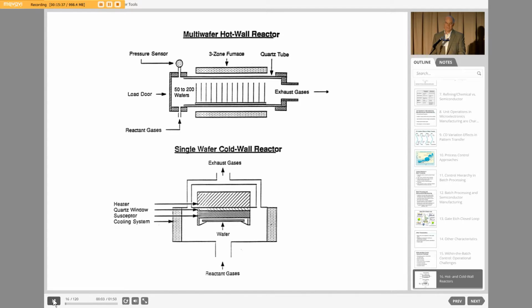In the 90s, basically we had multi-wafer reactors that we carried a lot of the steps out on. The top plot there is an LPCVD, low pressure chemical vapor deposition reactor. They would put anywhere from 50 to 200 wafers in there, and then essentially deposit silicon, polysilicon, for example, on the wafers. And this worked pretty well as long as you had only 4-inch wafers. Once they went to 6-inch wafers, they started finding that the uniformity of the wafer was becoming a problem because of the nature of the heat transfer in the furnace. And so gradually the industry moved towards single wafer control so they could actually do a much better job of controlling what happened on an individual wafer.